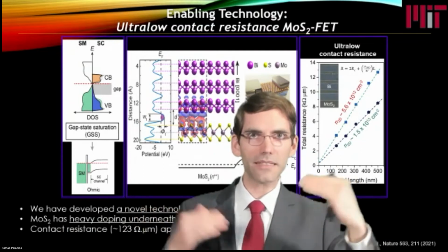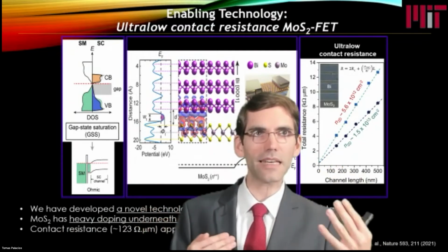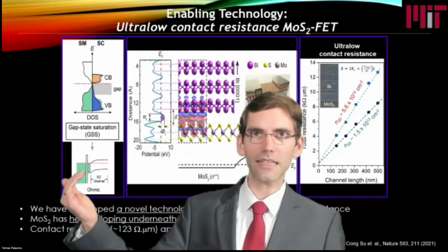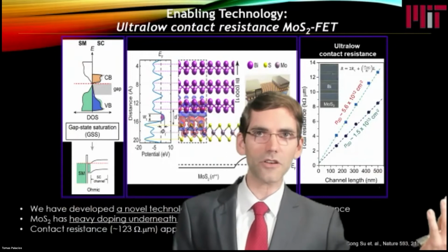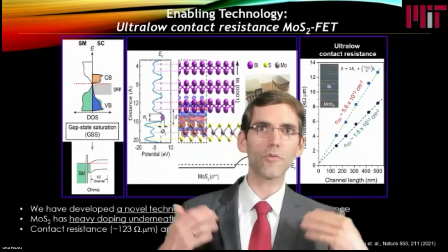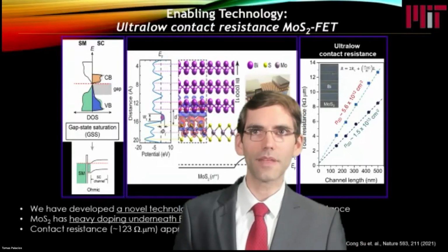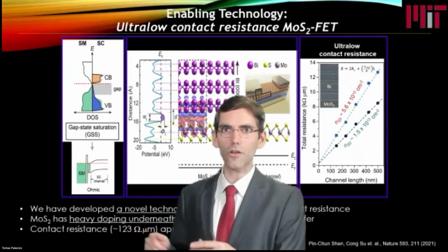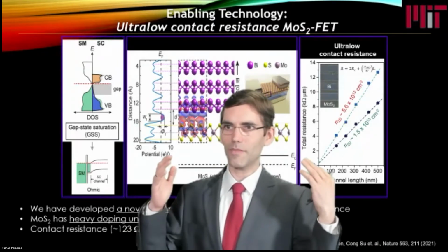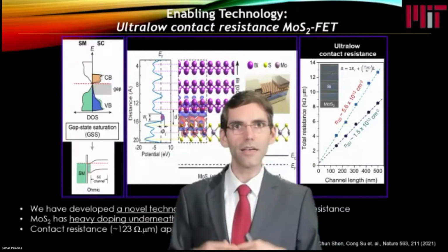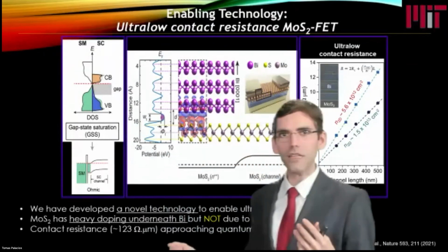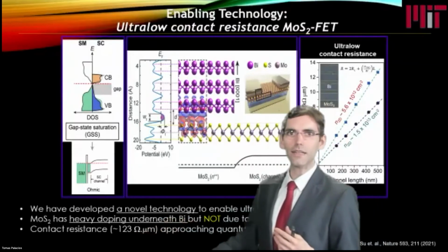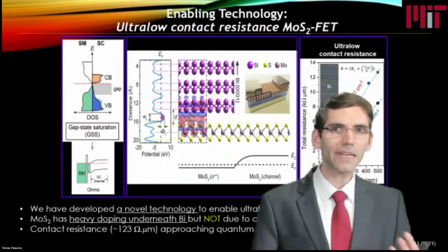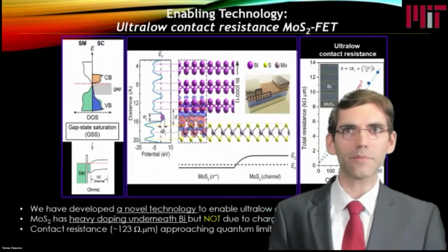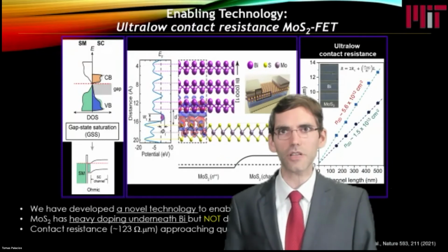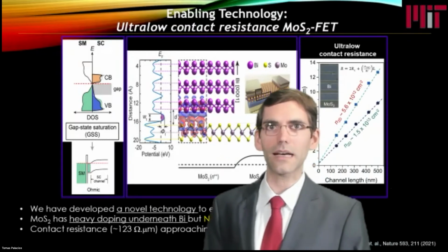And the hybridization, the number of hybrid states, the density of hybrid states that you can have between the states in bismuth and the states in molybdenum disulfide is going to be significantly lower than with any other more conventional metal. And by using that, and this is all proven by DFT simulations, etc. But by doing that, we were able to demonstrate a contact resistance to moly disulfide of around 120 ohms a micron, which is very close to the quantum limit for this material. This was the lowest contact resistance demonstrated to 2D materials, as far as I can tell.